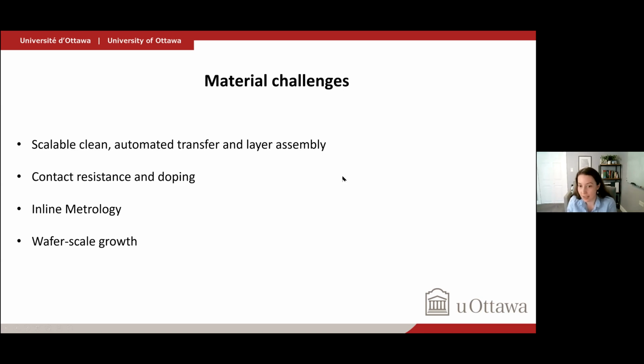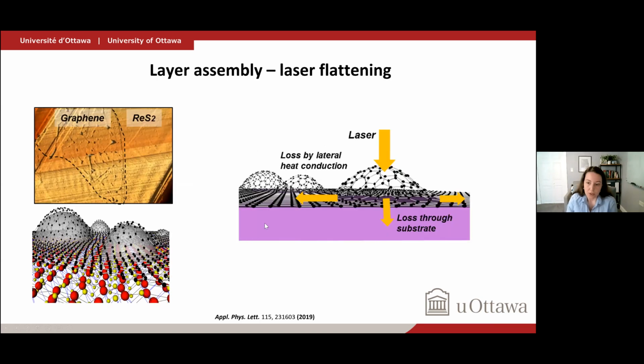So a lot of the things I'm showing you are sort of micron size devices. They're wonderful, but if we want to use them in devices, we want to also have a way to grow them at device scale. So work that we've done in this space, for example, is using a laser light to flatten. So as we transfer, let's say, graphene onto a semiconductor, we try and make these heterostructures, we find these ripples and wrinkles, which are as a result of the van der Waals interaction. Think of it as putting saran wrap on a surface, right? You'll have bubbles trapped in, and so on. But of course, we want to flatten these for devices.